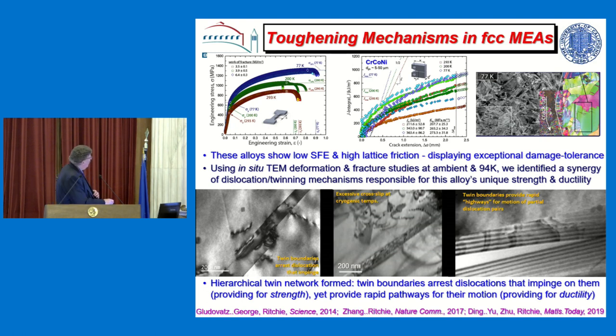We look at the R curves, so these are things on the toughness, and the toughness rises to massive amounts. In this material, the toughness gets as high as 273 megapascal root meters at liquid nitrogen temperatures. That doesn't mean much to many of you, but the toughness of steel at most would be 100 megapascal root meters. The toughness of silicon is 1 megapascal root meters, and these materials are up at 273.